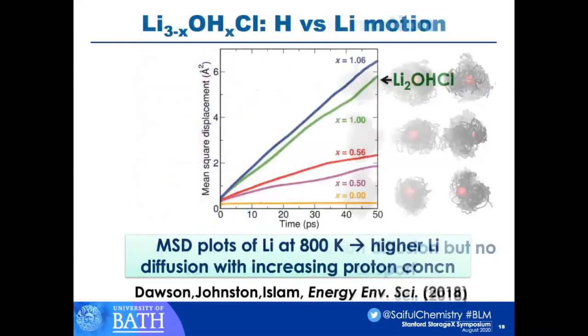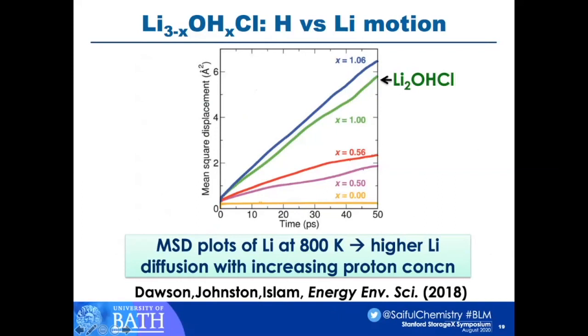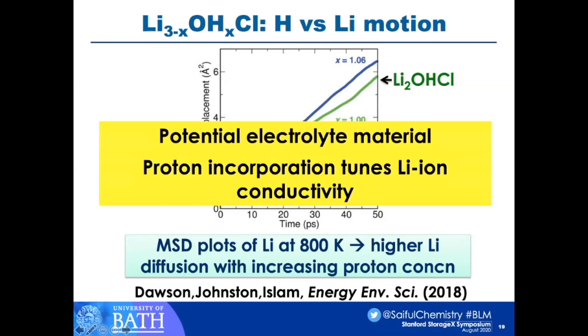We then looked at what would happen if we changed the proton concentration. We find that if we increase the proton concentration, by increasing the lithium vacancies, you can see that the conductivity goes up, the actual displacements go up. So we are finding a higher lithium diffusion with increasing proton concentration, which is quite nice because it's another sort of design tuning mechanism to increase the lithium conductivity. So the take-home message here is that this is seen as a potential electrolyte material. There are some challenges, obviously, but what's interesting is that the proton incorporation tunes the lithium ion conductivity.